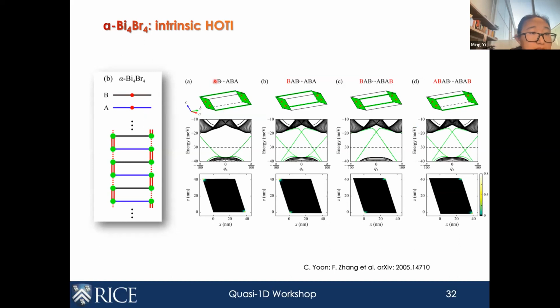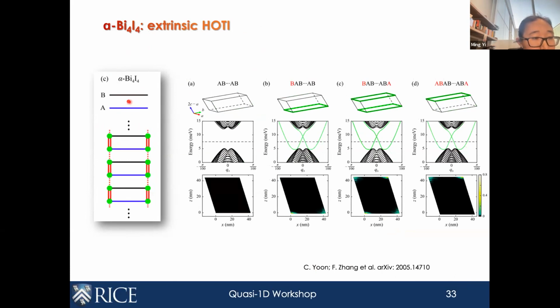So just to be more complete, for the alpha phase of bismuth bromide, where the inversion centers are within the planes, no matter how you terminate this, in the four types of termination combinations on top and bottom, you will always have edge states. Therefore, the alpha phase of bismuth bromide is an intrinsic higher order TI. In contrast, for the case where the inversion center is within the two layers, there's one situation out of the four where, if you terminate with even layers, you will have no edge modes, but for three of the four combinations of terminations, you can imagine you will end up with edge states. And in a real crystal, in a real experiment on the cleaved surface, you're bound to have probably combinations of these different terminations, and therefore the presence of hinge states.